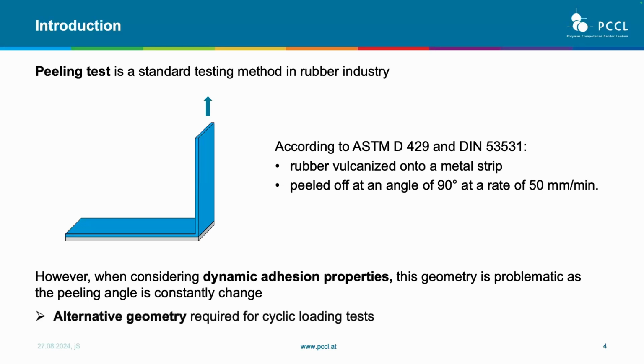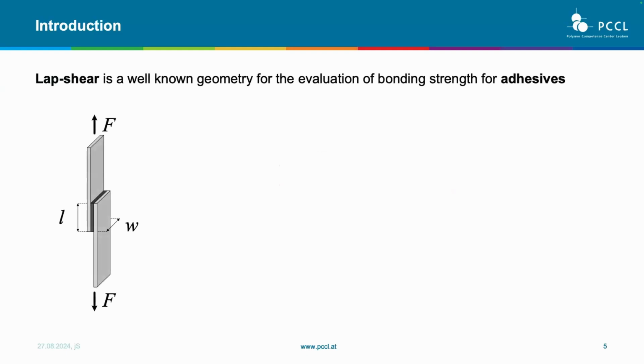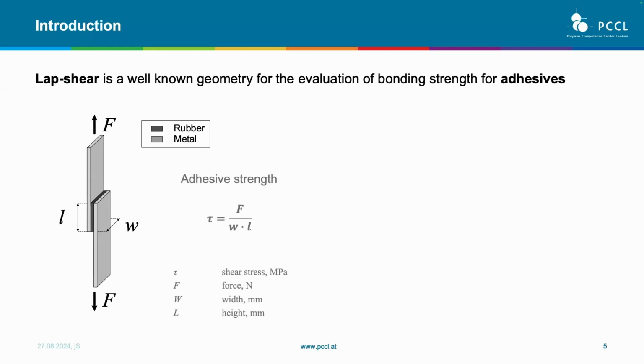So to tackle this, we thought about a new, different geometry. This geometry is the lap shear. Lap shear is quite common for the evaluation of adhesive strength. Our idea was to replace the adhesive with the rubber between the two metal plates. In this way, it's easy to calculate the adhesive strength in a shear mode. Clearly, the load is in this direction, but the adhesive experiences mainly a shear load.